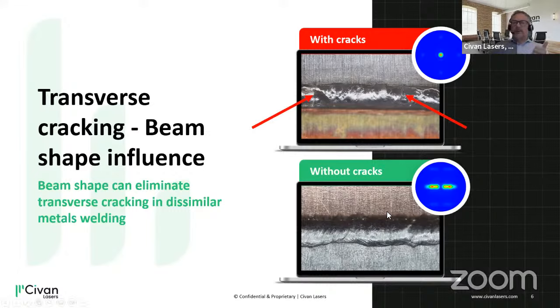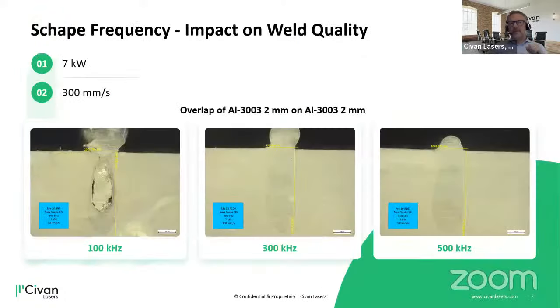Problems I mentioned before are typically humping. That means if you go fast, your topography of the welding seam gets unstable and you get humps. You can have cracks, and the last one is porosity. All that is basically driven by instabilities of the keyhole and the melt pool. And that's basically what we are all about. We are providing new means to manipulate the melt pool in terms of gradients, in terms of flow, and that's done mainly by controlling the keyhole.